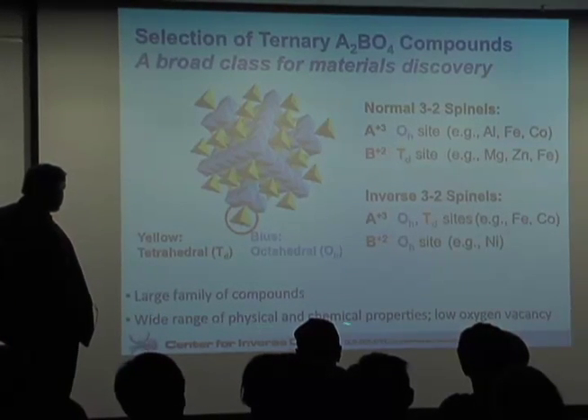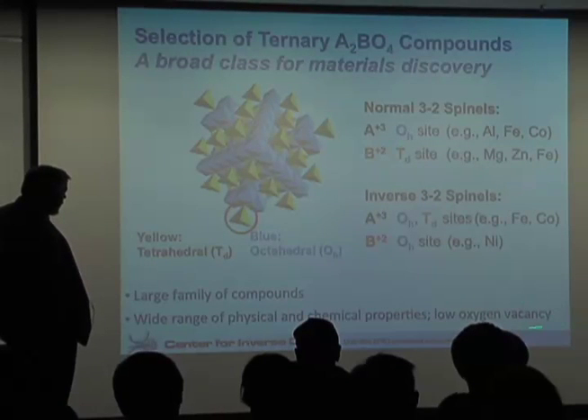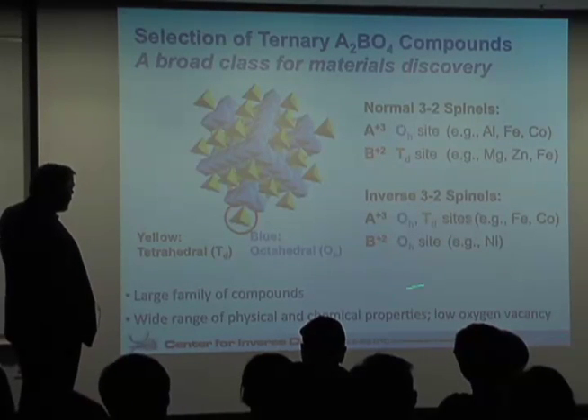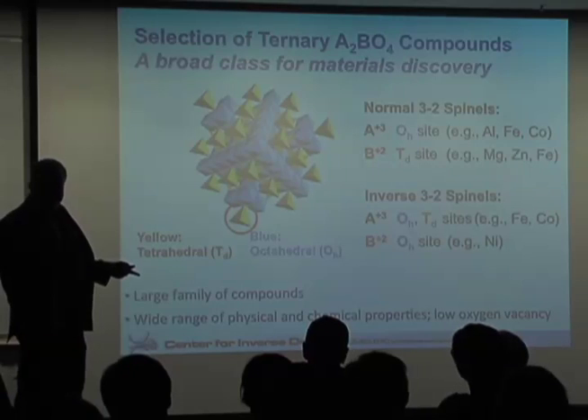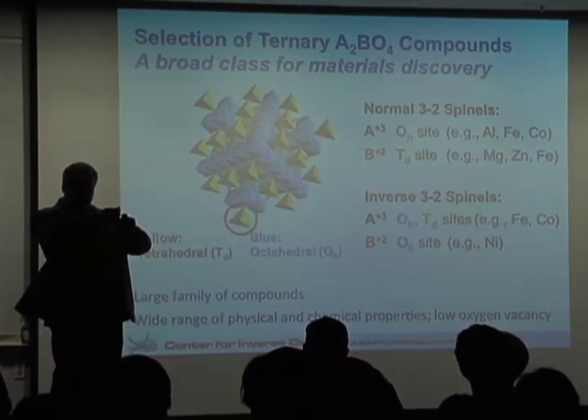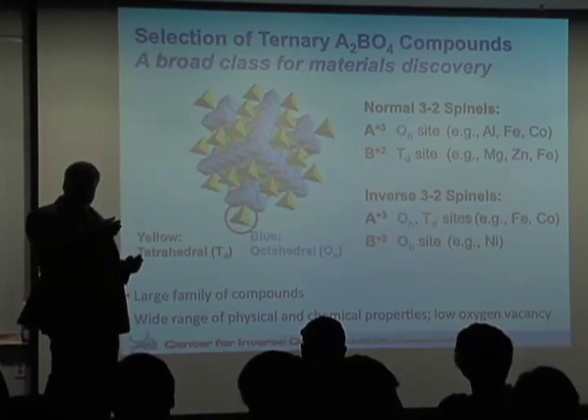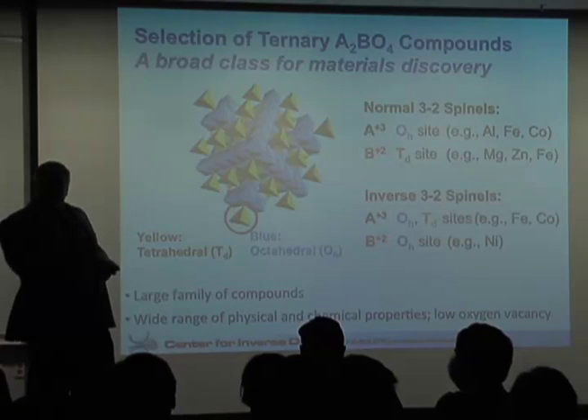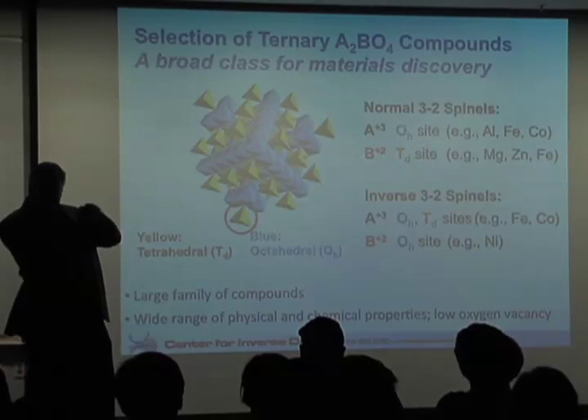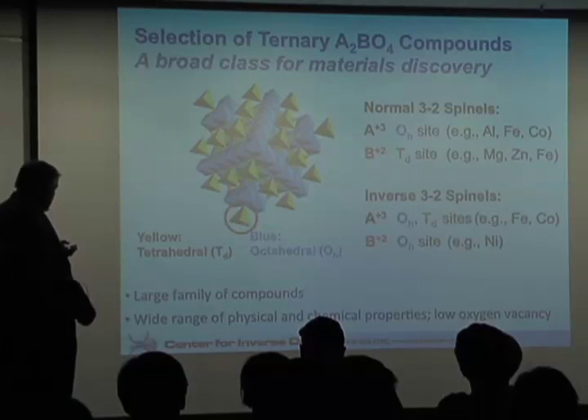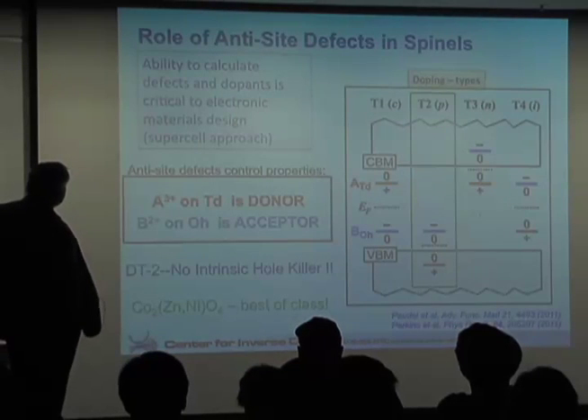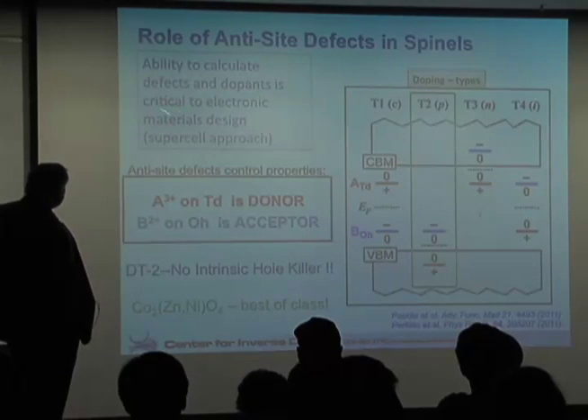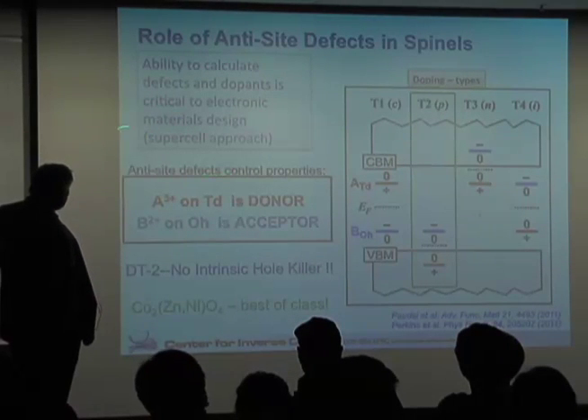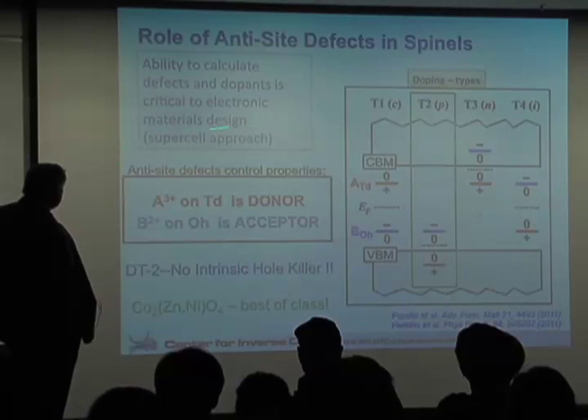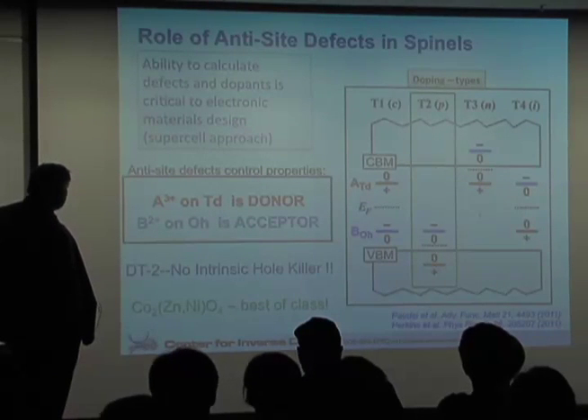So we've looked at these systems. Unlike other oxides, spinels turn out to have very low concentrations of oxygen vacancies, and they don't really have any interstitials because they're able to move back and forth. And so the primary doping mechanism in these systems are these anti-site defects as opposed to conventional, say, binary. So we did a lot of work looking at calculating dopants and defects, and that's critical to our whole design here. We have the supercell approach that we've used to calculate the energies of defects.